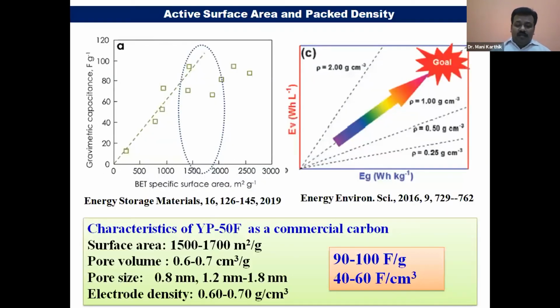See here, I said capacitance is directly proportional to surface area. That is true, but not only surface area; it depends on your activation condition. You can reach a surface area up to a maximum of 2,500 square meters per gram, but there is a limitation: commercially only 1,500 to 1,700. You need a good tap density because you must coat your material on the surface of the current collectors. A very porous, spongy structure is not possible to coat on your current collector.